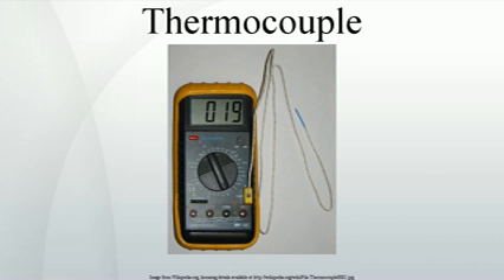In some cases a special grade, special limits of error, is available, that offers a closer match to a standard curve. High-grade thermocouple wires can have a high cost per unit length, making it expensive to run them over long distances to voltage measuring instrumentation. However, changes in metallurgy along the length of the thermocouple, such as from termination strips or changes in type of wire, will introduce another thermocouple junction which can affect measurement accuracy. To solve this problem, extension-grade wires, the cheapest and lowest quality, are used to carry thermoelectric signals over a long distance between a high-grade thermocouple and a measuring instrument some distance away. While the high-grade thermocouple may be used at extreme temperatures, the extension-grade wires are only intended to be used over a narrow range of temperatures, typically only -50 °C to plus 100 °C.